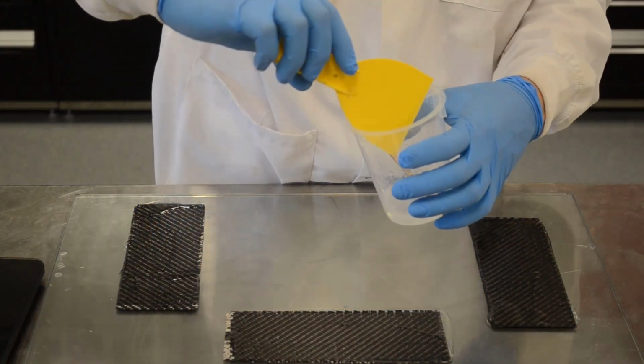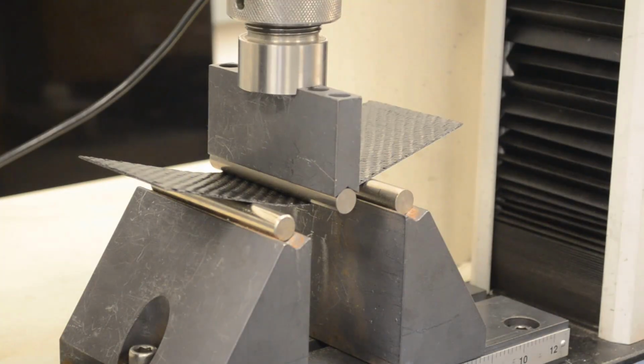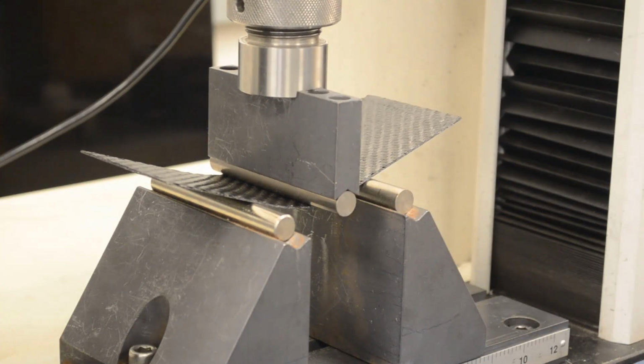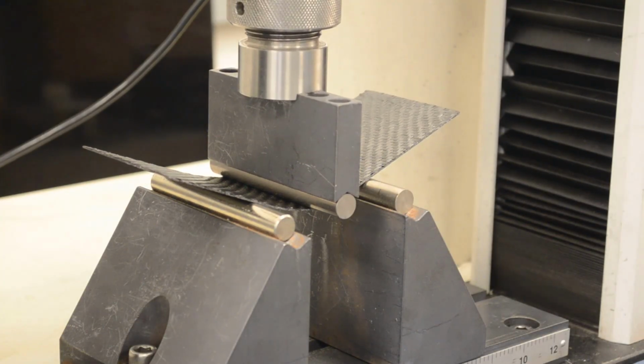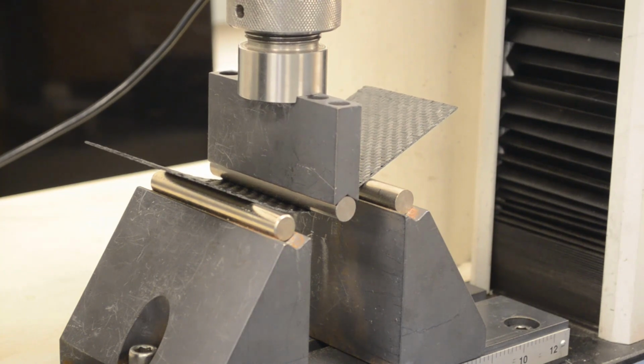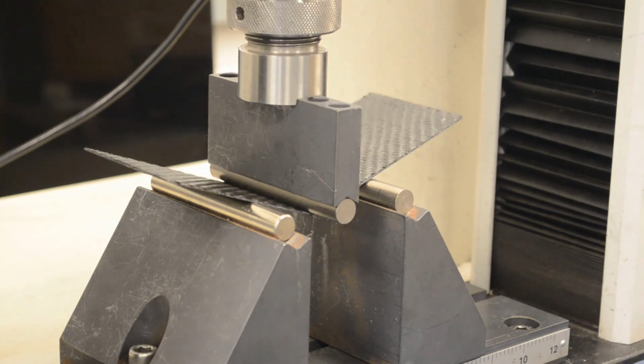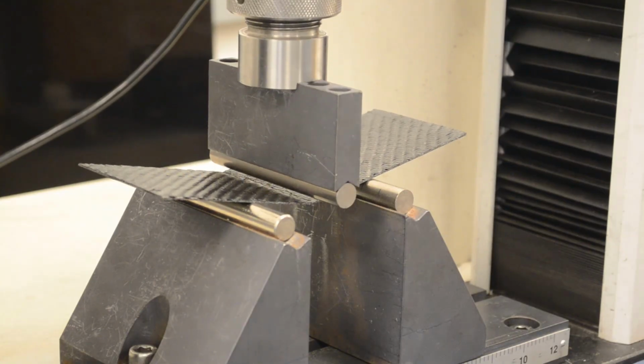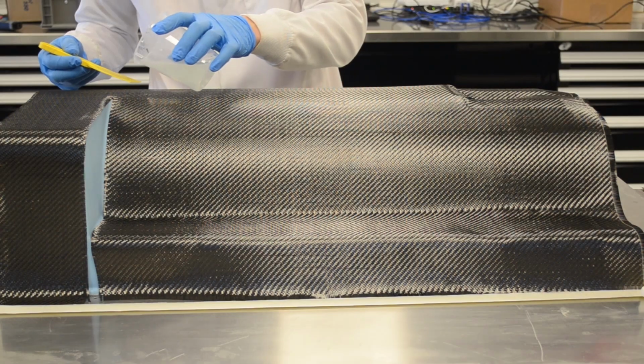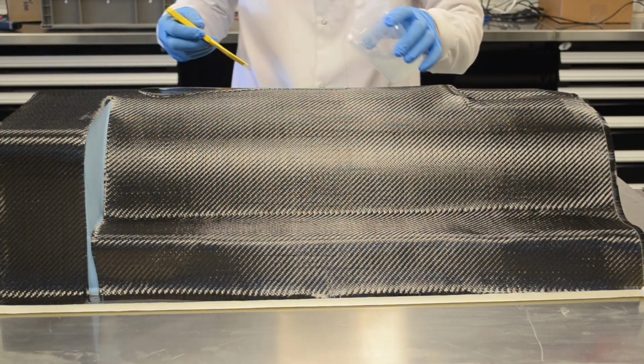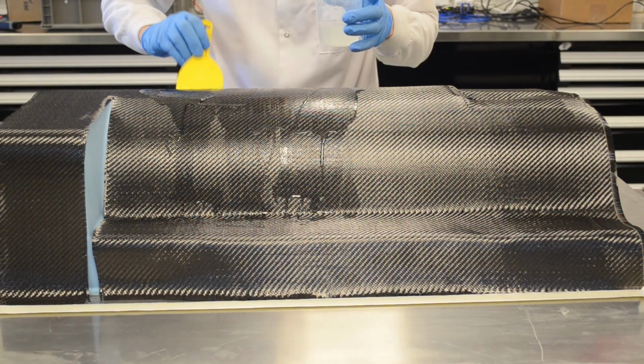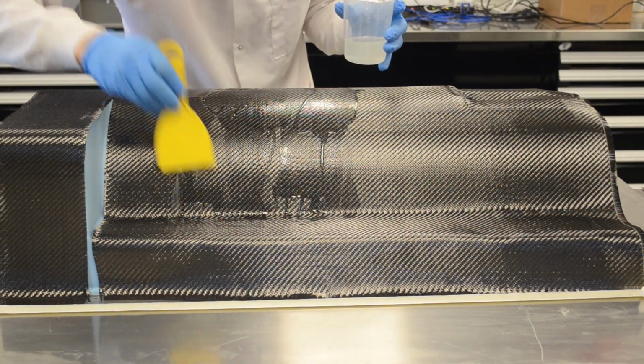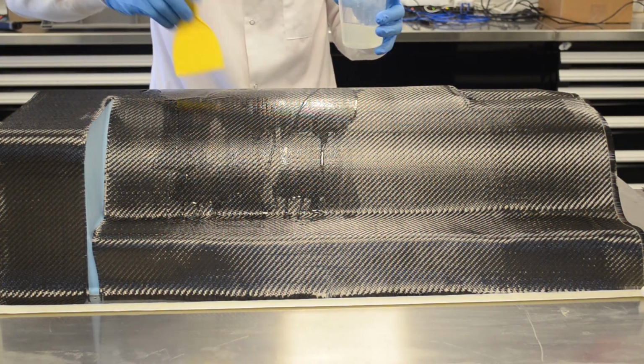These results are from a 3-point bend test of a relatively thin part made with woven fabric in a wet layup process. If any parameters are changed, such as switching from woven fabric to unidirectional, or performing a different test or using a different sample geometry, the results may also change. We will now perform a wet layup of a more complex part to showcase the effect some process parameters have on part quality when difficult geometry is present.